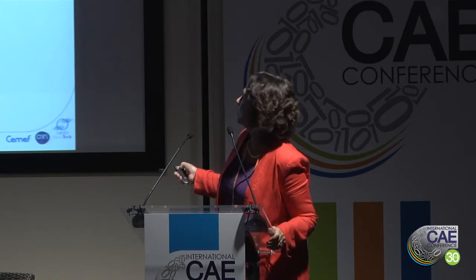Okay? And here it's very interesting. It's the nucleation, the growth and the coalescence of this void. Here a real image, and here the finite element simulation of this using this level set approach. We have the growth of this void, so you notice that it's not really a spherical part, it's really a 3D simulation with a coalescence of the two. There are more details on the poster given by the young PhD student, Modessa.